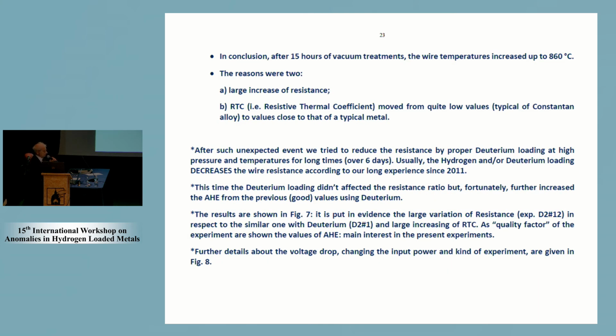The reasons for such a large temperature increase are two. One, we detected a large increase of resistance. The second one, because the material changed, we have a large resistivity thermal coefficient. So two effects in the same direction.